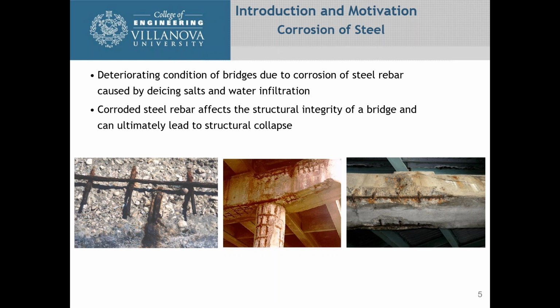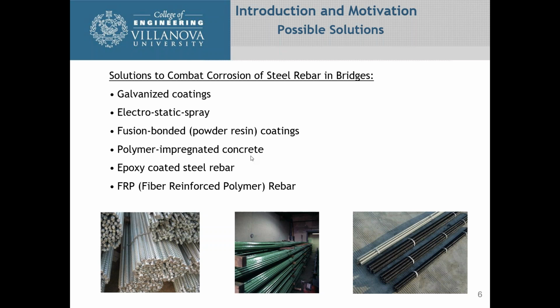In these pictures here, you can see typically what happens. Now, there has been the advent of going with epoxy-coated rebar, but that has not eliminated the corrosion in the steel of the reinforcing. So, possible solutions that are currently on the market now are galvanizing the reinforcing bars. You can do an electrostatic spray, fusion powder, resin coating, polymer impregnated concrete, epoxy coated rebar, or look at using fiber reinforced polymer rebars. Primarily, the epoxy coated reinforcing bars and the galvanized coatings are the two most commonly used in the United States at this time.